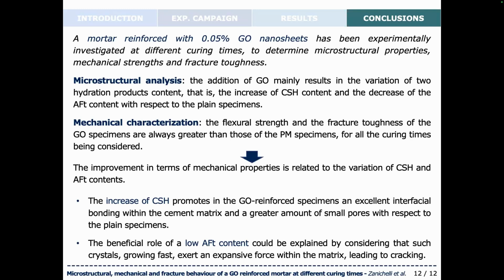In the present research work, cement-based materials reinforced with 0.05% of GO nanosheets have been experimentally investigated at different curing times to determine the microstructural properties, the mechanical strength, and the fracture toughness. So as far as the microstructural analysis is concerned, the addition of GO mainly results in the variation of two hydration products content, that is the increase of CSH content and the decrease in the ettringite phase content.